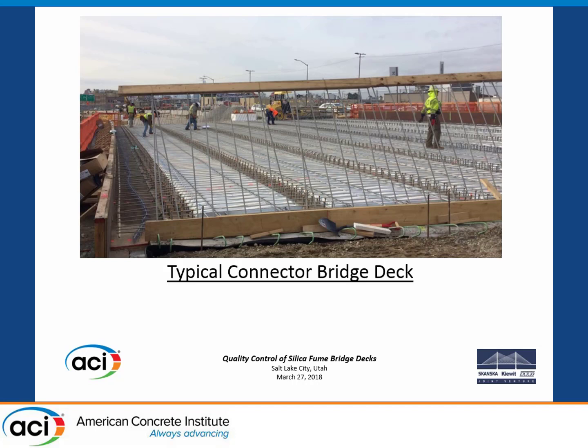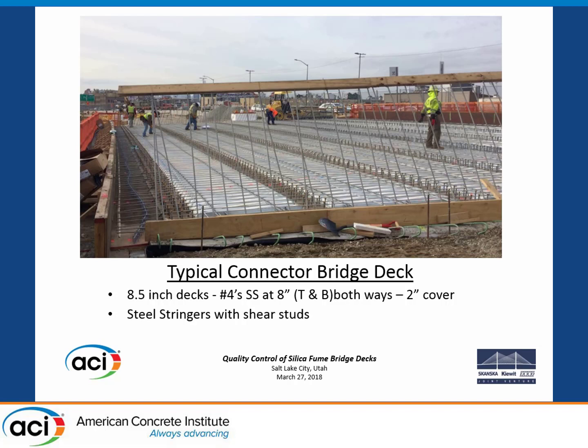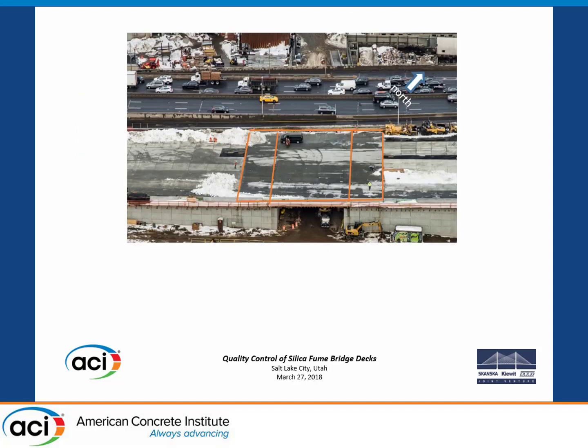This typical connector bridge deck is the 8.5-inch deck, number 4s on 8-inch centers, top and bottom both ways, 2 inches of cover. It's steel stringers with shear studs on them. If you notice, the back wall dowels are locked into the deck. They're turned up right now so the laborers can set the bar. And then there are also bars coming out of the back wall that lock into the approach span. That's a lot of restraint. You got tons of studs in there, and you got steel beams, then you're locked into the approach back walls.